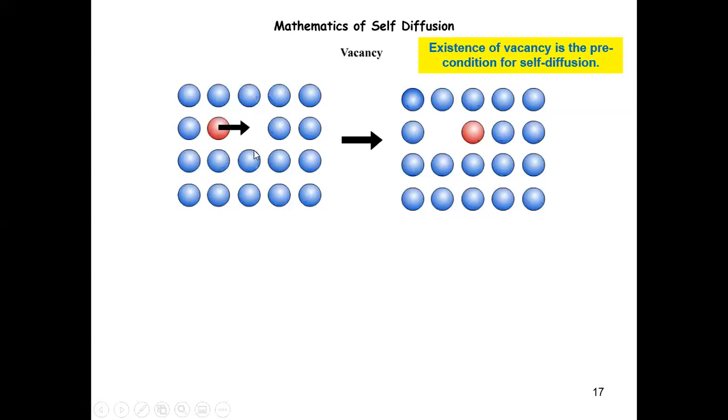In the interstitial diffusion case, we know that the particles are taking these sites, right? And in most of the cases, we're only looking at a low concentration of interstitials. So they're almost free to move around and free to hop into any of the neighboring sites. But here, for a substitutional atom, it's quite different. It has to wait until there's a vacancy nearby and then hop into this vacancy site, right? So that's, intuitively, the difference between diffusion of different types of atoms.